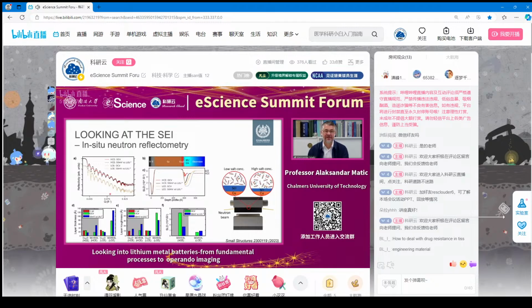And here we could see, for instance, that comparing a highly concentrated electrolyte and an electrolyte with low concentration, we could see that actually for a highly concentrated electrolyte, the SEI is much thinner. It's also less rough. And also we could see that it contains much more inorganic species. So this is a very good method for directly following this. Unfortunately, this method is not, at least not in the present form that we have been working with it, suitable for doing real-time measurements operando.